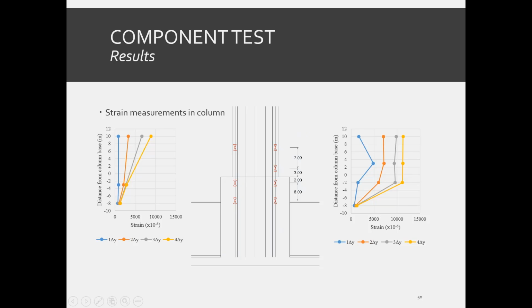The specimen was instrumented with strain gauges on column longitudinal rebars. Results show that the strains in the reinforcement inside the cap beam did not increase substantially. However, the strain gauges on rebars close to the cap beam and column interface showed significant strain on these bars. The strains in the plastic hinge region showed an increase as expected.